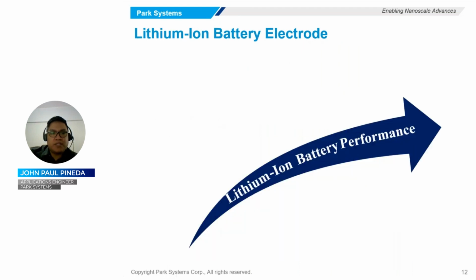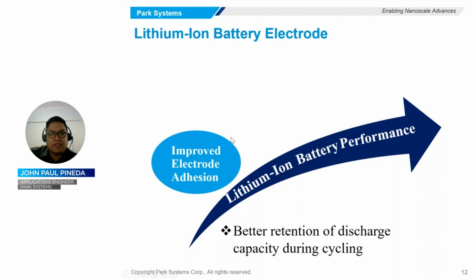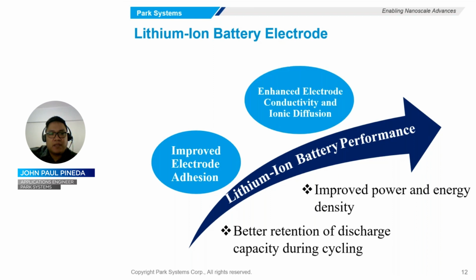So let's move on to the lithium ion battery performance improvement. Previous studies say that understanding the electrical and mechanical properties of electrode materials plays a major role in the performance improvement of LIB. It has been shown that improved adhesion between electrode particles, electrode films, and current collectors leads to better retention of discharge capacity during cycling, especially when electrode materials exhibit faster or larger volume expansion. In addition, enhanced electronic conductivity and ionic diffusion in electrodes also lead to LIB capacity improvement.